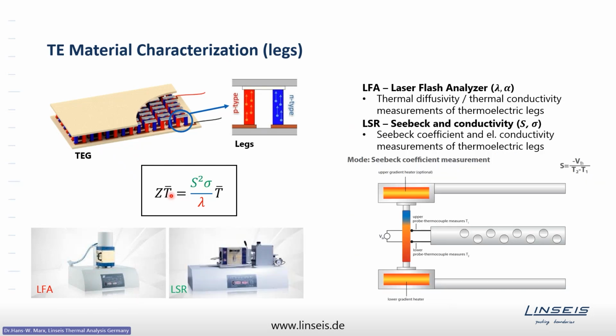Additionally, the Seebeck coefficient and the electric resistivity have to be measured. This is done by the so-called LSR machine, LSR standing for Linseis Seebeck and electrical resistivity. In such a machine, the thermoelectric material is placed between two holders, one of them containing a heater, so generating a temperature gradient throughout the thermoelectric material. And from the side, you have temperature probes and voltage probes measuring the voltage drop and the temperature difference. And by dividing this voltage by the temperature difference, you get the Seebeck coefficient.